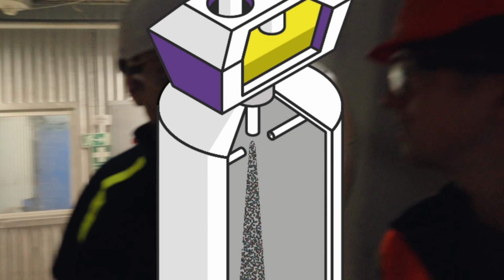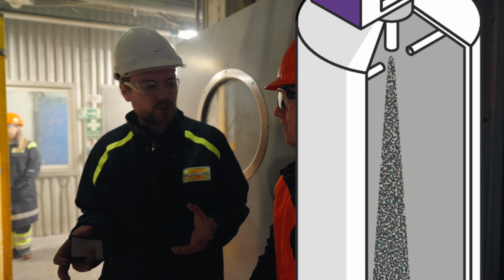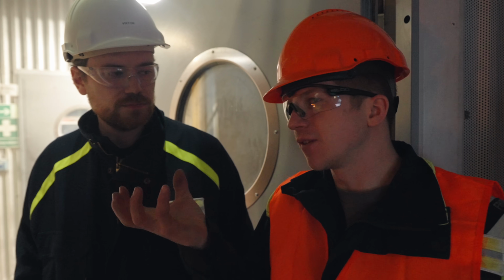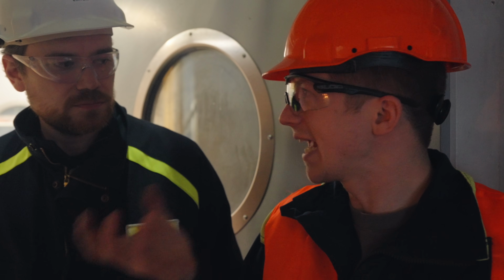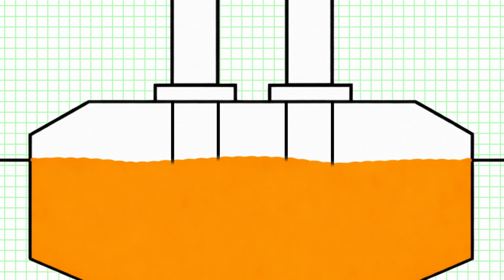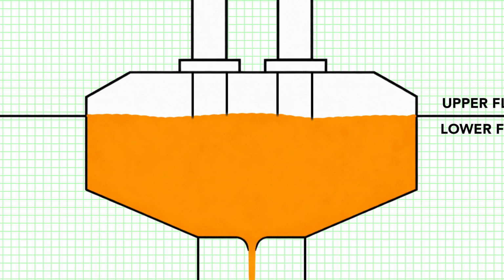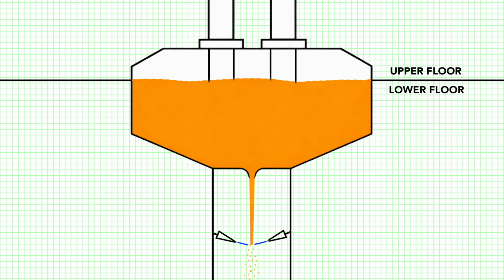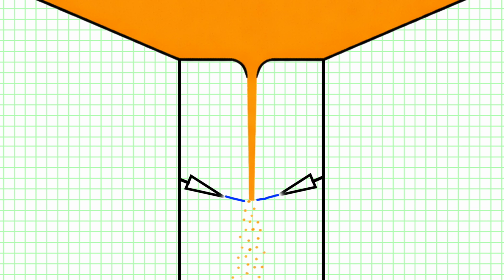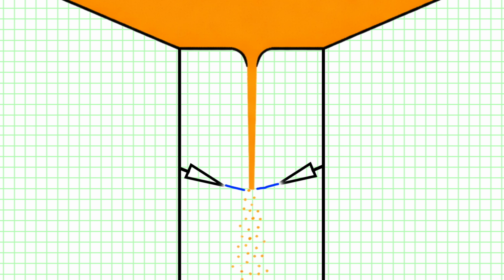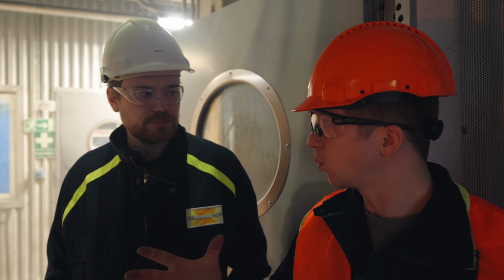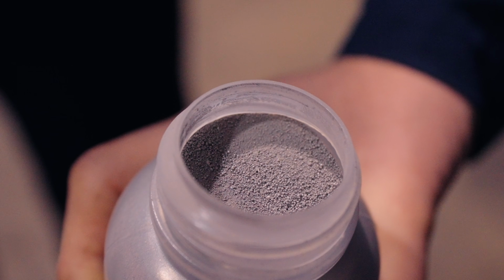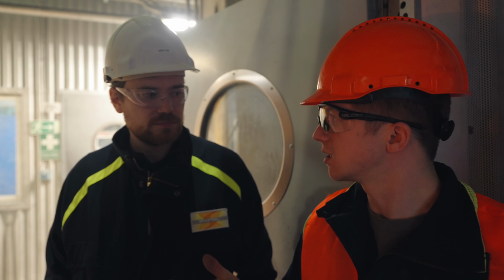There it is in contact with two gas jets shooting supersonic nitrogen gas onto the liquid steel, disintegrating it into small steel droplets. So effectively, the tundish is that container of molten steel. Correct. You've dropped it down into the ground here, and then you're tapping from the bottom in a small hole where you're then blowing jets of nitrogen to atomize it. Correct. And turn the liquid into those tiny, tiny grains that are going to immediately freeze and solidify.